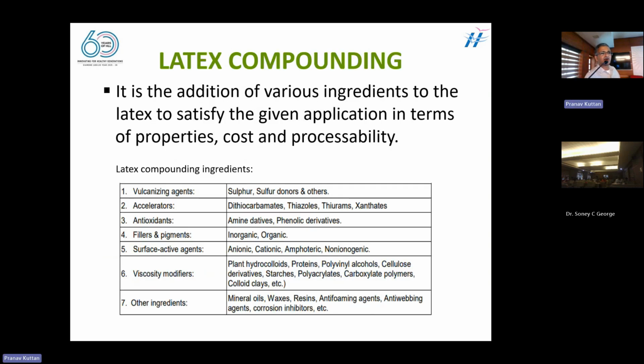So in order to do the compounding of latex, we use several agents to impart the properties. We have to add sulfur to make the cross links between the carbon chains. So we require sulfur. This is a major vulcanizing agent which is used for natural rubber latex. Natural rubber latex can also be vulcanized without sulfur. They can be vulcanized by other processes called radiation and peroxide vulcanization. There are also other methods. But the common commercially used method for imparting elasticity and strengthening rubber is sulfur as the vulcanizing agent.